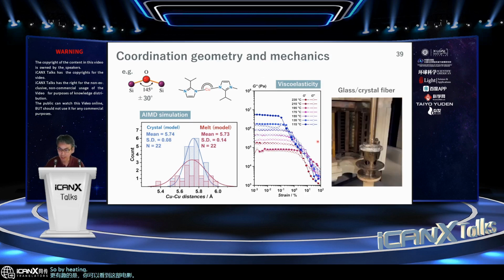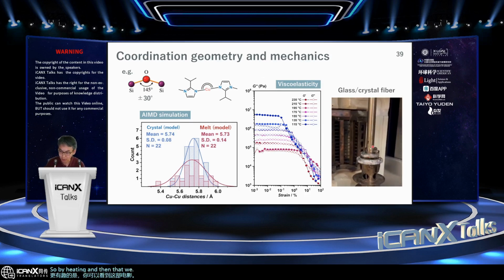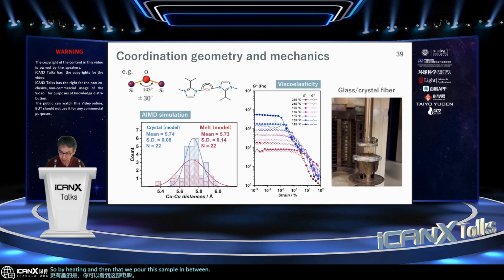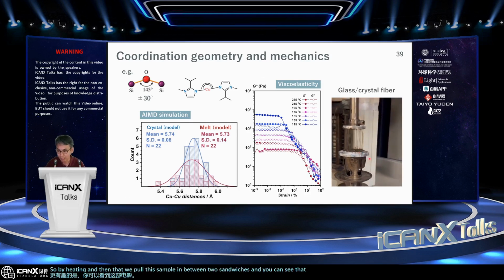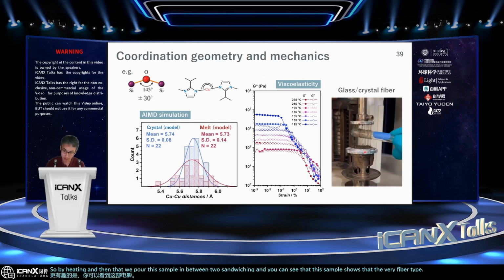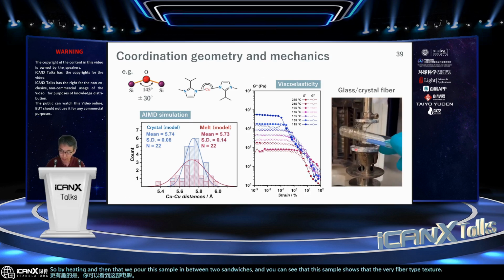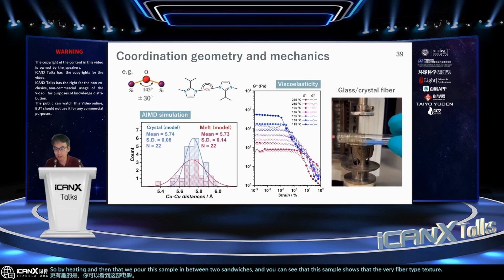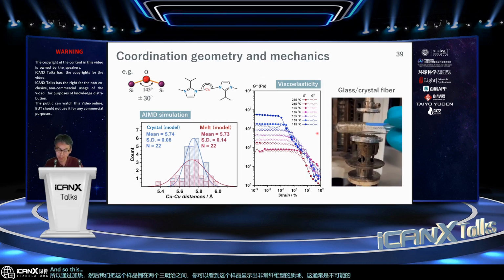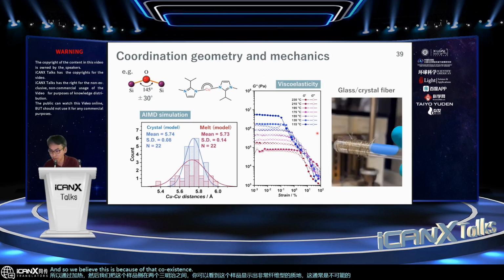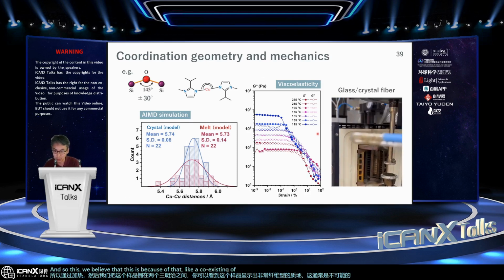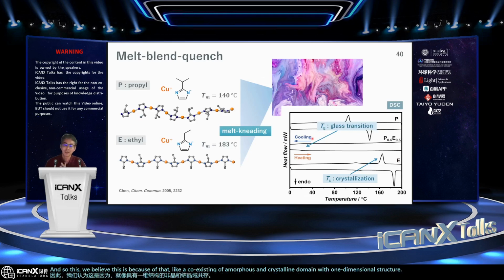So by heating, we pour this sample in between two sandwiching plates, and you can see that this sample shows a very fiber-type texture, which is normally impossible with crystalline, brittle MOFs. We believe this is because of the coexistence of amorphous and crystalline domains with one-dimensional structure. So we are more interested in the relationship between organic polymers and, let's say, the one-dimensional MOF, the phase changes.